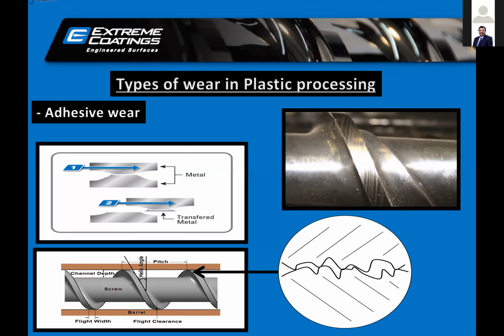In adhesive wear, when you purchase new screws and barrels, the surface may look very smooth, but in microscopic view, the surface has peaks and valleys, and when two peak points come in contact with each other, because of the higher shear they create a micro weld. This picture may give you more explanation. It has nothing to do with hardness actually. It's just that these two high points melt with each other because of the higher shear, and because the screw is rotating, it ruptures. And that's how adhesive wear starts.